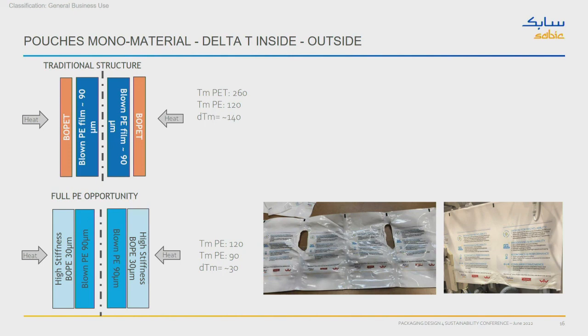If you change the melting temperature of the inside of the film, you put it on a reel in summer, maybe not only here but also further south. I think in Spain it's over 40 degrees. If I come to the factory, I need to be able to unwind the film. And if it is then sort of molten together, I have an issue. I cannot unwind the film anymore. I cannot use it anymore. So we had to do a lot of work in that respect to optimize outside of the film versus inside of the film, to be able to make a standard pouch out of a monomaterial solution.